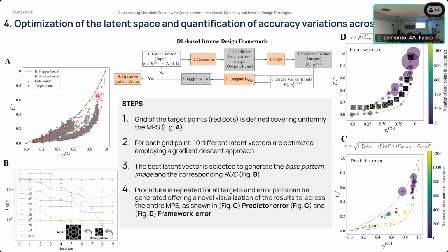Moreover, if we repeat this for all the target points in the material property space, we can create this kind of error plot that allows us to quantify the error across the material property space, in order to correlate the accuracy of this framework with the availability of the training data. And how do we do that? In these plots, the radius of these circles is proportional to the error, and the color encodes the density of training data in the neighborhood of the target point. Therefore, in a single plot, we can observe the relationship between the accuracy of the framework when targeting new designs and the availability of training data associated with that particular target point.